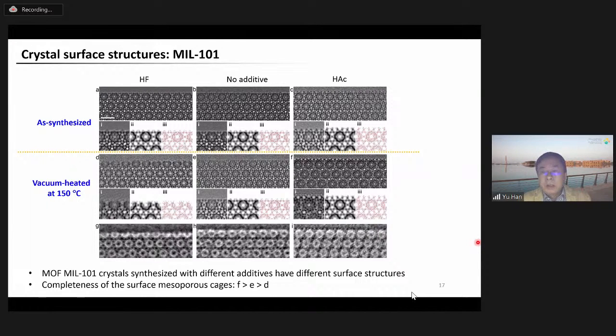So here we use the completeness of the mesoporous cages to describe the states of the outermost surface. And we identify three different types of surfaces in these samples, as you can see from images D, E, and F here. After vacuum drying at 150 degrees, the sample synthesized with HF shows very open cages at the crystal surface. In contrast, the sample synthesized with acetic acid shows completely closed cages on the surface. And the sample synthesized without any additive shows a state in between. So we identify three different surface structures.